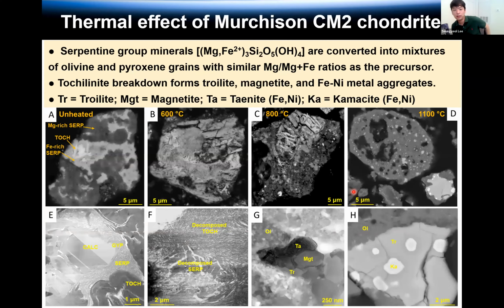So now move to the heating experiment of Murchison CM2 chondrite minerals. This is the initial sample, and then I heated to different temperatures. This is 600 Celsius degrees, this is 800 Celsius degrees, and this is 1100 Celsius degrees. So at 600 Celsius degrees, I can see that some serpentine decomposition happens. So decomposed serpentine and decomposed tochilinite. Decomposed means they become something like an amorphous phase, like very poorly crystallized phases.